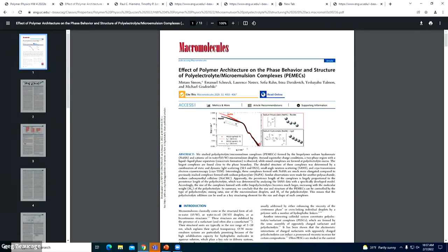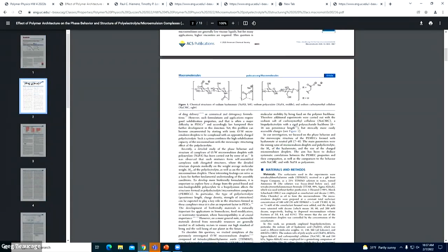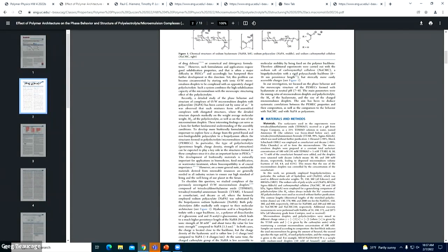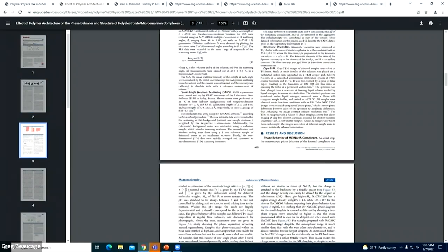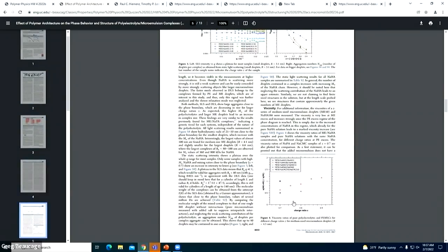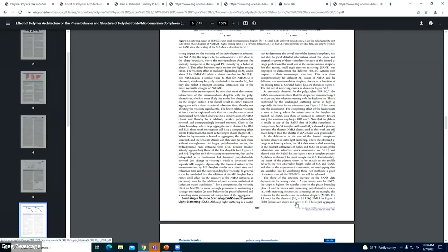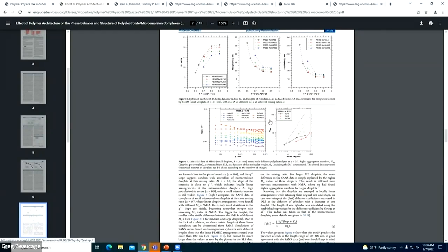He's using different techniques. Like this is neutron scattering. Then he uses dynamic light scattering to get the hydrodynamic radius, and then he uses static light scattering to get the number of spheres. So he uses kind of 3 different techniques. So it might be that they don't agree with each other, or the samples were different, who knows. But basically that's what he reports. He gets that the persistence length drops with the charge, which could be screening.